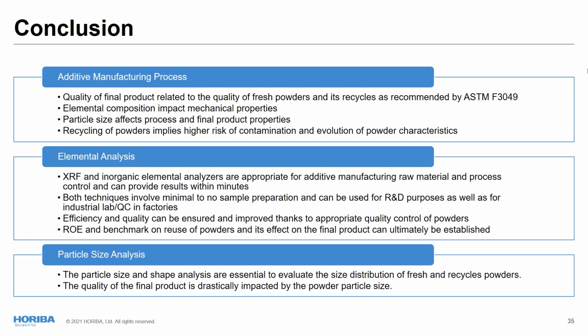characteristics. For elemental analysis, definitely the X-ray fluorescence and inorganic elemental analyzers are really appropriate and really easy to use for additive manufacturing, both for the raw material, the fresh powder, and also the process control, and typically will provide results within minutes. Both techniques involve minimal to no sample preparation, and can be used for R&D purposes as well as for industrial labs or QC in factories, really close to the process.